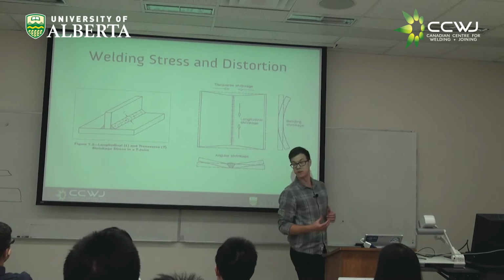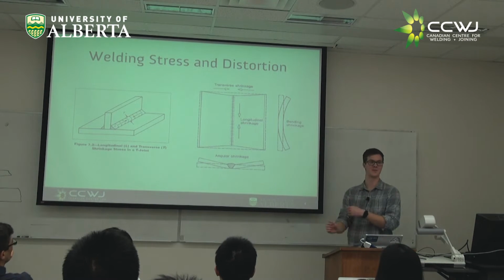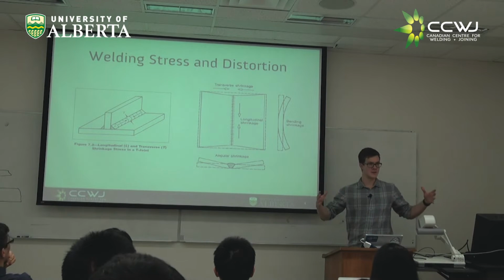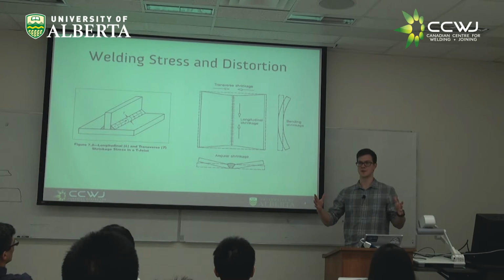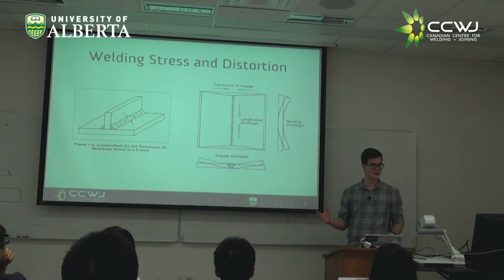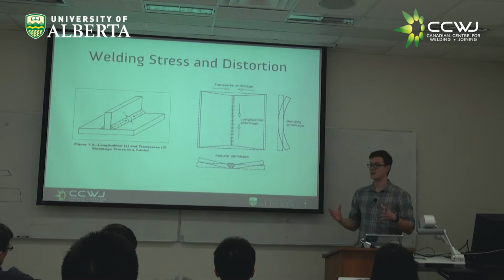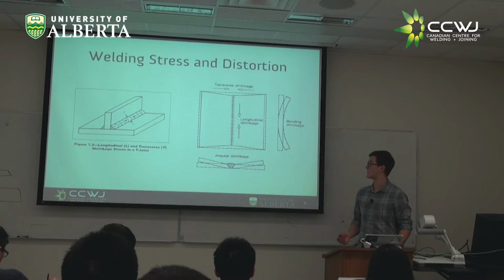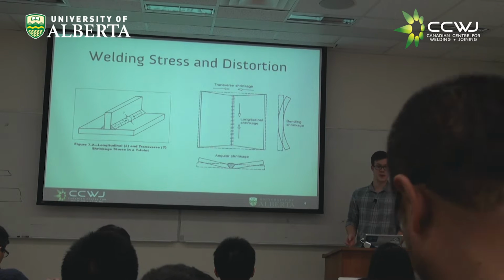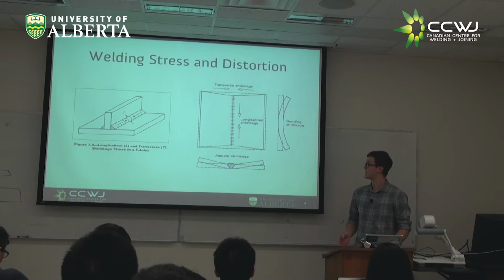So if you imagine you're welding two pipes together, actually that's a diagram I don't have up here, and you've got really long lengths of pipe, there's not a lot of restraint there. The pipes can actually kind of act like two big springs, where your stress across the weld is not going to be as significant as your stress in the direction of welding. So the longitudinal shrinkage, which is what we're going to spend most of class talking about, is that stress in the direction of welding. And typically, that's going to be the stress that causes the most issues in pipeline welding, and in a lot of cases, it's going to be the stress that causes the most distortion that you're worried about.